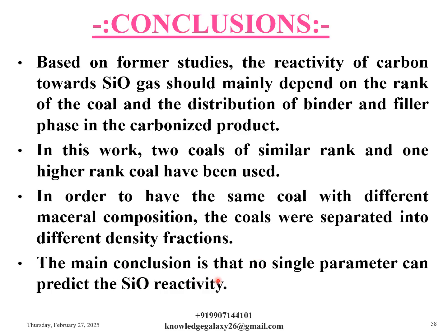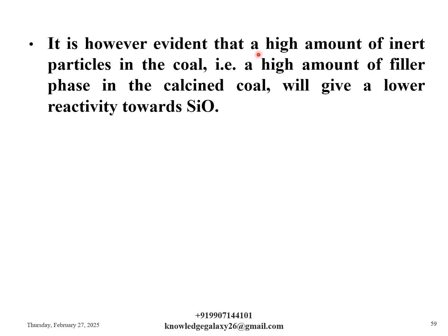The main conclusion is that no single parameter can predict the SiO reactivity. I am repeating this line as it is very important. It is, however, evident that a high amount of inert particles in the coal, that is, a high amount of filler phase in the calcined coal, will give a lower reactivity towards SiO.